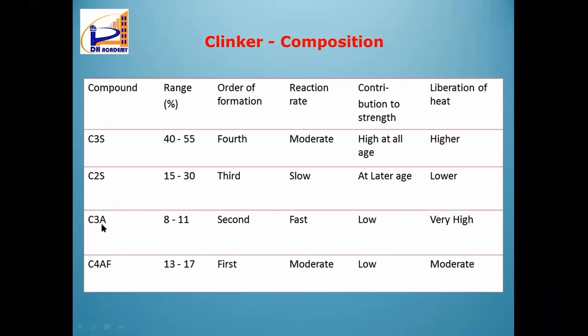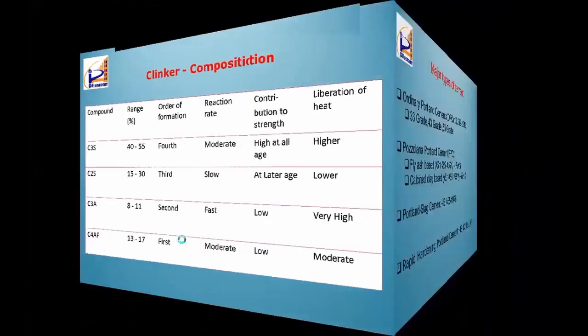C3A, tricalcium aluminate, is also very less in quantity, but the reaction is very fast. C3A will react very fast, and the heat generated is very, very high, the most in concrete after hydration. And C4AF, tetracalcium aluminoferrite, is moderate, with low heat generation. Because of this tetracalcium aluminoferrite, we are getting the gray color of cement, because of its presence.